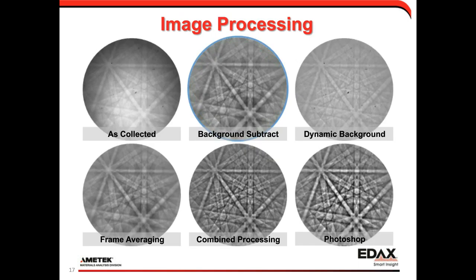So if we put these all together, you can see, basically what we want to do is get away from the as-collected image where there's a strong intensity gradient and low contrast, and get to some amount of processing which will show a flat-fielded image with contrast that allows us to detect the bands correctly. When we talk about indexing and preparing a sample, we're not worried too much about what we need to do to get a pretty pattern. We want to be able to get indexable patterns reliably across the representative surface.